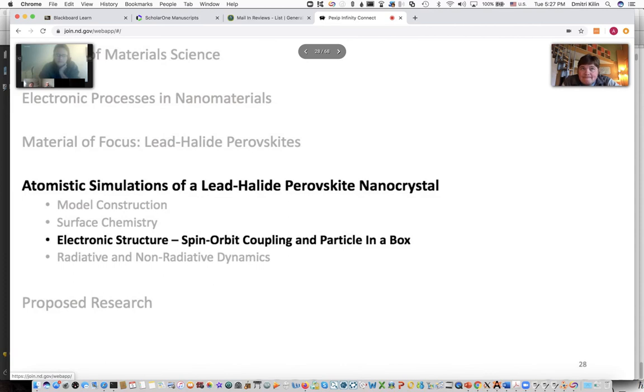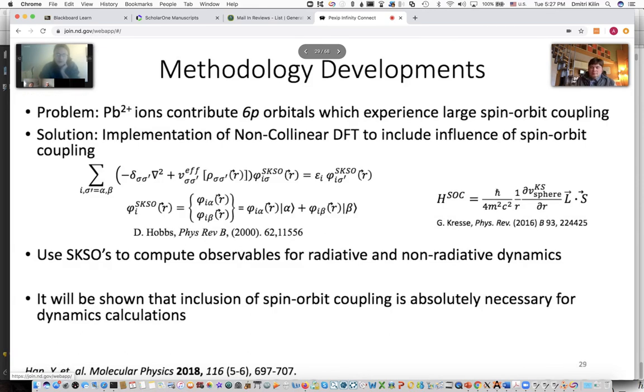So we construct our model, and then using the DFT density functional theory software, we optimize the geometry so that it reaches a stable minimum point. And just to give an overview of intellectual contributions we apply to this model, there's one technical problem where these lead ions, for the electronic states we care about, they have these 6p orbitals, which have a very large spin orbit coupling. So essentially that means that the electrons in the valence of these orbitals experience very large rotational motions in a sense. And so you can't use conventional DFT methods to get correct electronic structure.